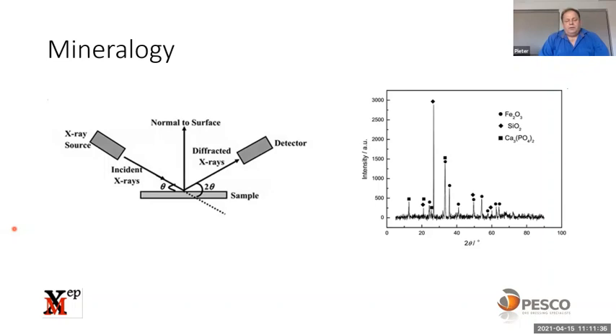Okay, so after you've done all your sample preparation, you will start with your mineralogy. The first step is using an XRD. The XRD is used to determine the mineral phase of the sample. It's X-ray diffraction, where you illuminate your sample. There's a beam on the sample, and it will generate various peaks. You see on the right-hand side, there's a graph. That peak will tell you what type of mineral it is.